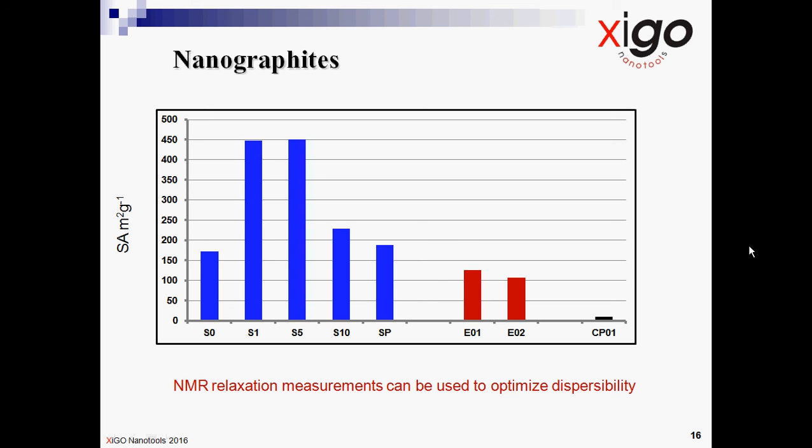These data show us that the different preparation methods used with E1 and E2 do indeed lead to differences in the total wetted surface area. And it is important to note that since the surface chemistry is assumed to be the same, we would be able to see the effect of the change in milling techniques even without having measured the relaxivity constant for this interface.